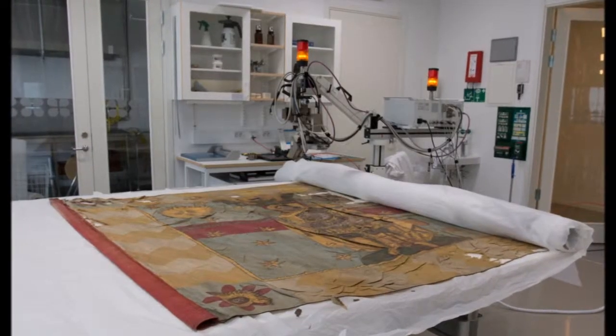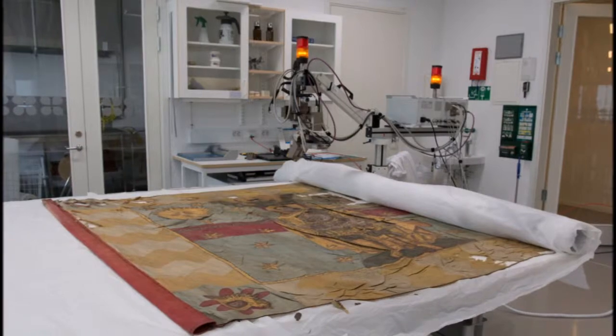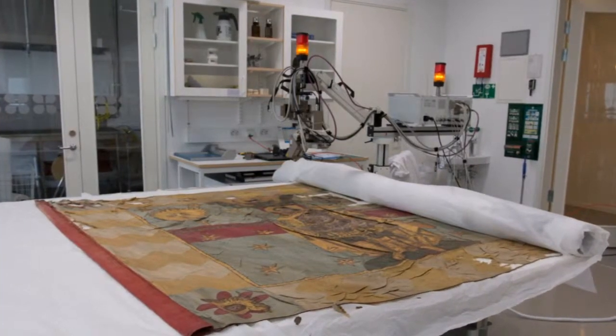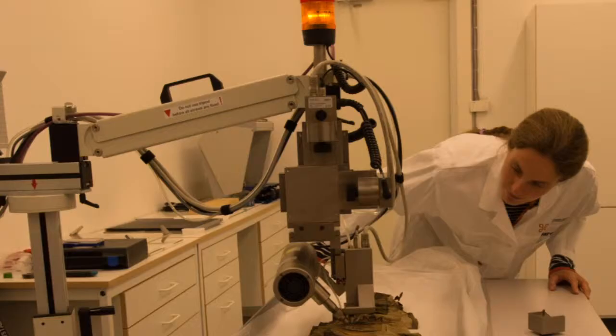Using micro-XRF, it is possible to carry out non-destructive material analysis on a very small surface. Here, on the Saint's harness on the Streltsy colour, we looked at the silver paint, which proved to be lead white, and the halo shows high levels of gold. We also looked at material in the pennant, such as the paint on the eagle's wings and on its label.